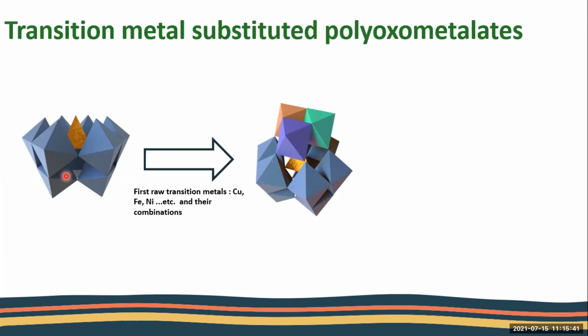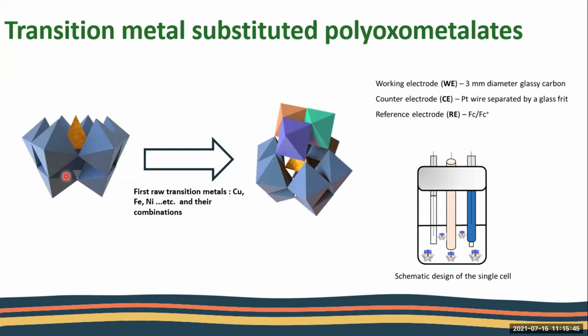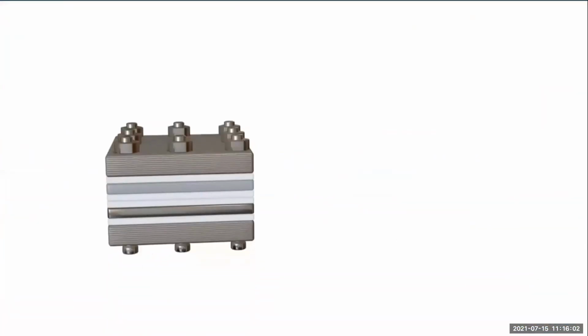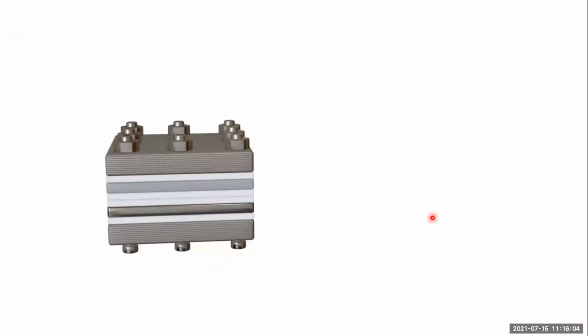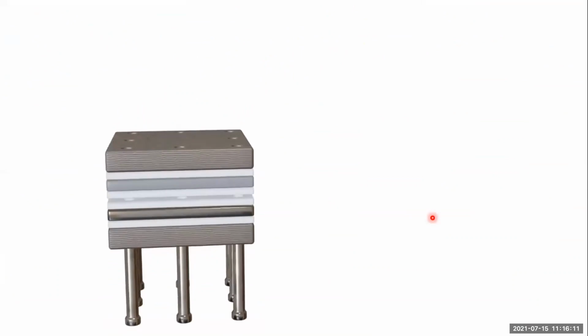And we checked the electrochemistry by using first an undivided cell that includes 3 different electrodes. We use glassy carbon as working electrode, platinum wire separated by a glass frit as counter electrode, and ferrocenium as reference electrode. And at some stage in the project, we used a divided cell that includes 2 electrodes that are separated between them with a Nafion membrane.